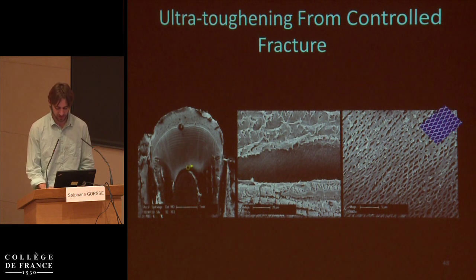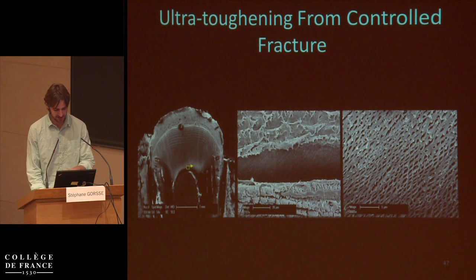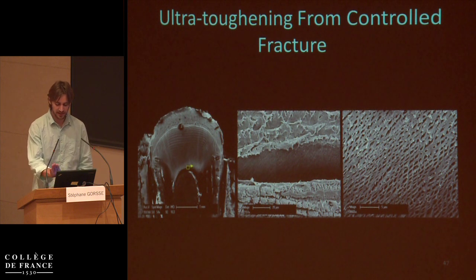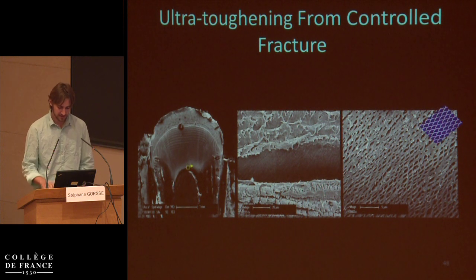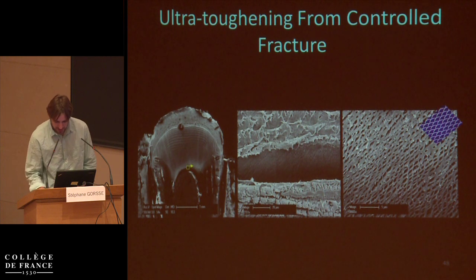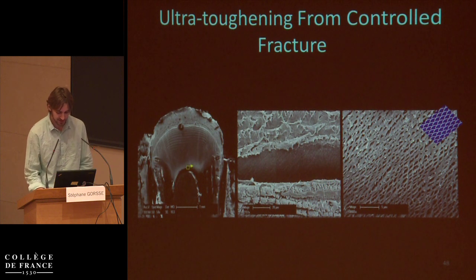And so I'll explain why you would want to do that. So that you can see, this is a demineralized surface, and there's a very small little delamination here. And I've zoomed in, and so you can see a single layer of chitin. And it's just littered with microporous channels that go through the thickness of the fiber layers. And to me, it looks something like expanded metal, that's what that picture is.